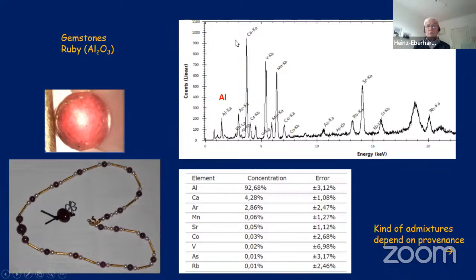And we get a lot of intensity, at least it looks like, for the concentration of the impurities or admixtures in the system, like here the calcium, manganese. The value of the ruby pretty much depends on the impurities. And to give you a comparison, here you don't see any gallium.